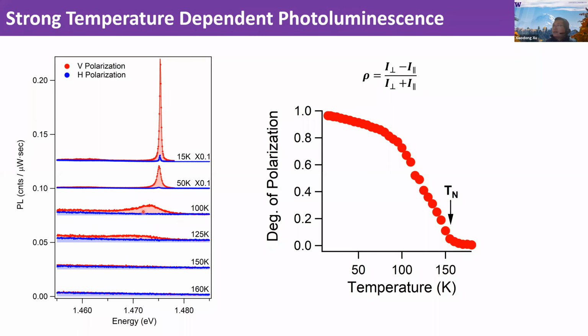Two things stand out. The first is the peak gets much broader above 100 Kelvin, and the second is the intensity really drops, and the signal basically vanishes above 150 Kelvin. This data already suggests the luminescence has a strong connection to the formation of zigzag antiferromagnetic order, but the origin of the linewidth and intensity changes has some complicated effects. For example, temperature, like phonon effects, can also affect the linewidth and intensity. So the quantity we can really look at is the degree of linear polarization, as I show here: the intensity of vertically polarized light minus the horizontal, normalized by the sum. We plot this degree of linear polarization as a function of temperature, and it almost vanishes above the Néel temperature.